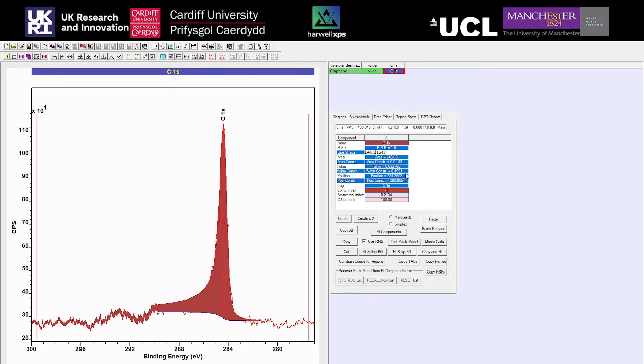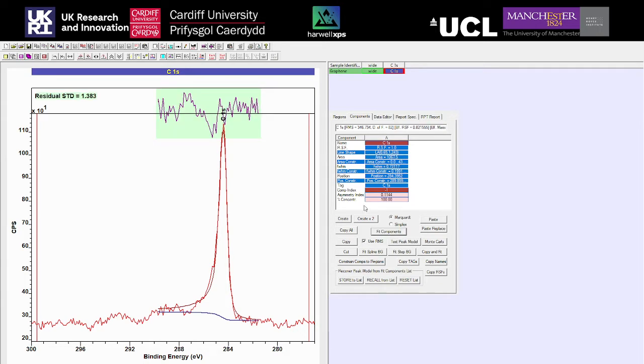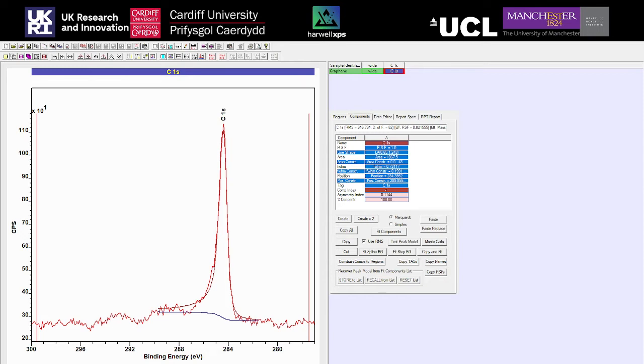The low binding energy side looks like it fits quite well already just with a value of one, so we'll leave that and just modify the other side. Bringing it up and fitting — we're getting close, just moving up in increments. It's probably somewhere between 0.6 and 0.7; we'll try 0.65. We've now got something which is going through the high binding energy data. One feature you can use to assess how well your peak model fits is the residual up here. Anything around one and below is good; with noisier data it's generally harder to get residuals to decrease due to signal-to-noise.